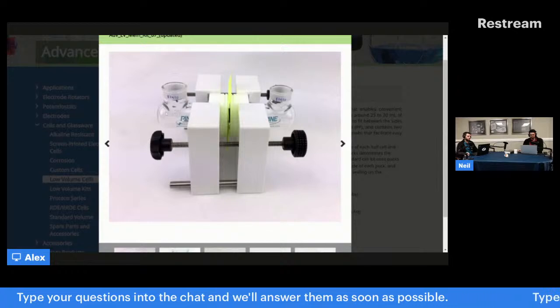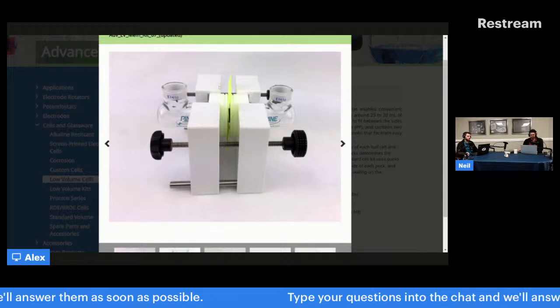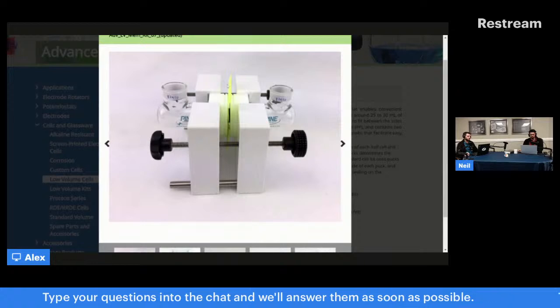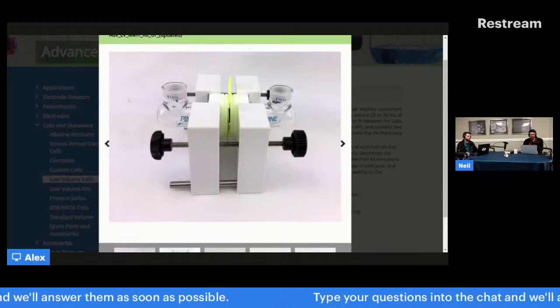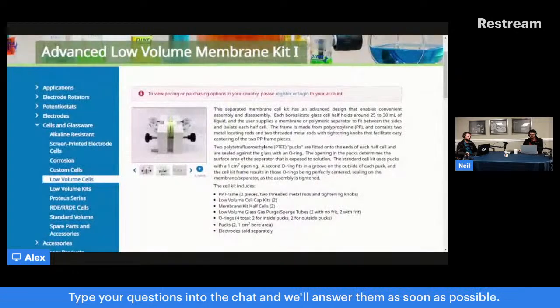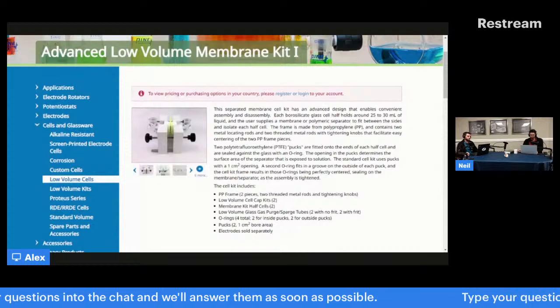So that would be the way you would determine the impedance, and then you take 1 over that to get what the conductivity is. That is a way you can measure the conductivity for your membrane. And so you'd have to pick whichever electrolyte. It'll depend on the electrolyte and the composition, but generally speaking, that is what you would do to calculate your conductivity. Hopefully that was helpful. If you need further clarification, please let us know.